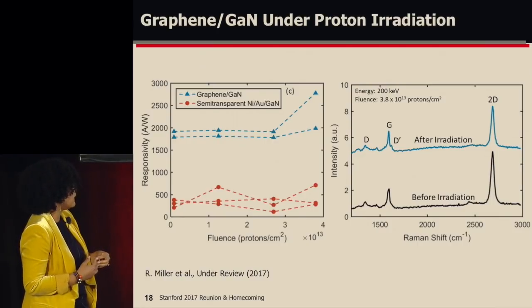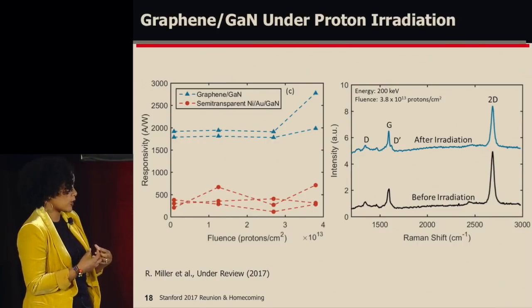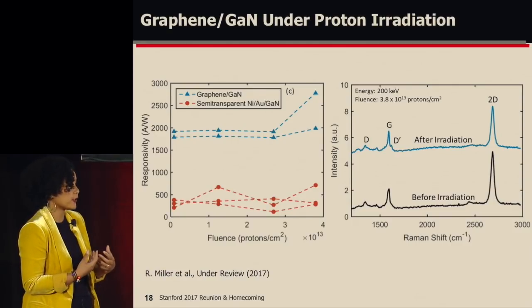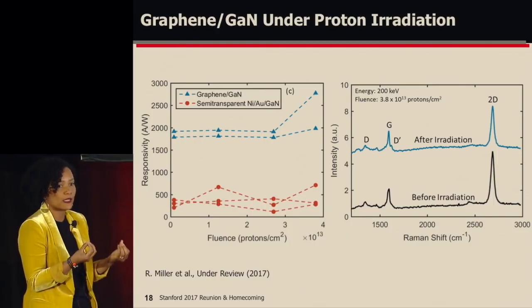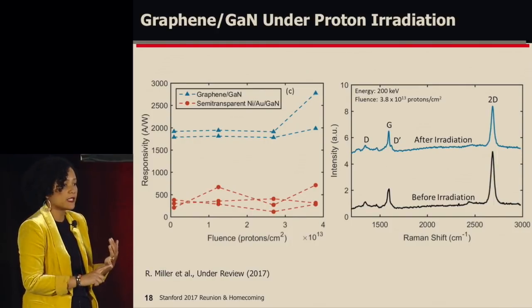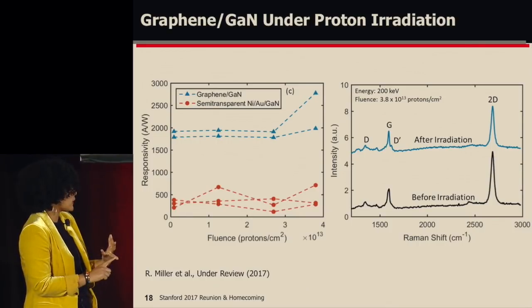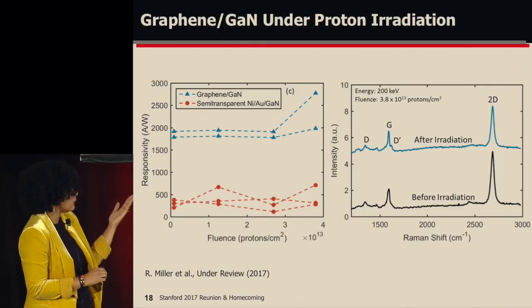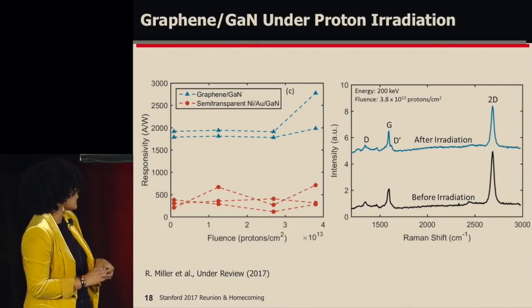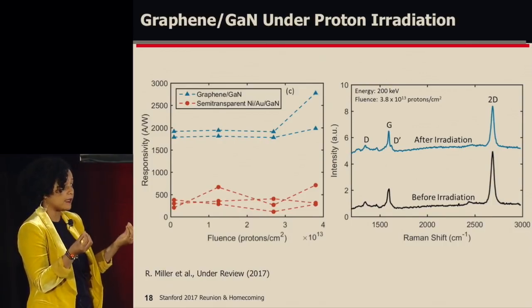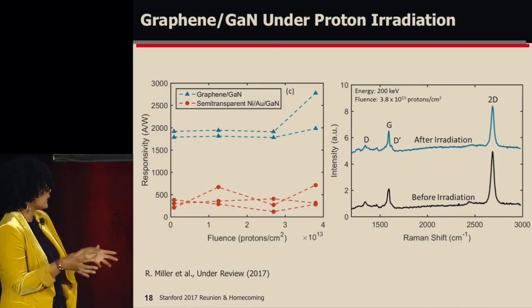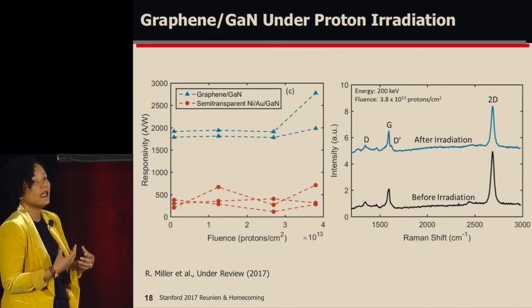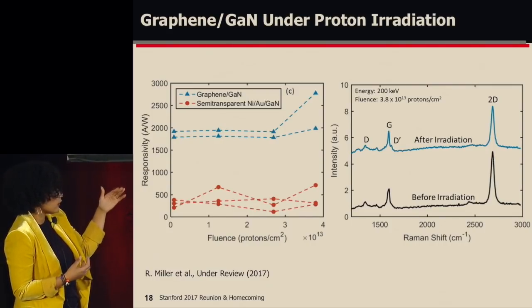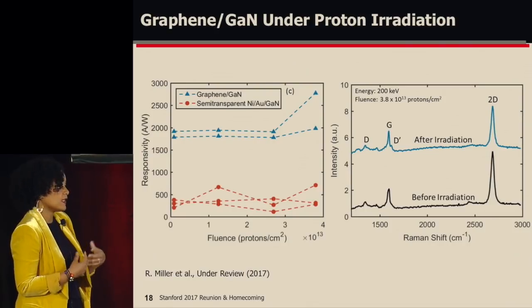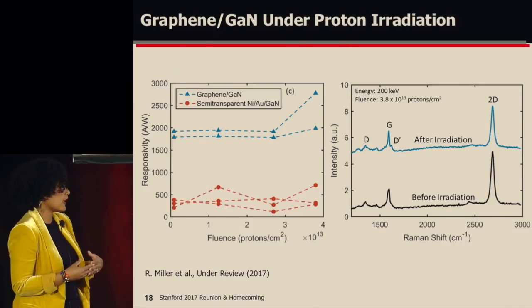We've also studied the response of the graphene layer using Raman spectroscopy. Raman spectroscopy is a materials characterization technique. It actually allows us to get the fingerprint of the material. We can identify the type of material and also the crystallinity of the material. So what you're seeing here is the graphene before the proton irradiation and after proton irradiation. And you can see we're getting sharp peaks. So this 2D peak is a very high intensity peak, and that tells us that the graphene is of very good quality. And after radiation, we see minimal degradation in that peak. And so that's telling us that even after an intense irradiation, this nanomaterial is able to survive.